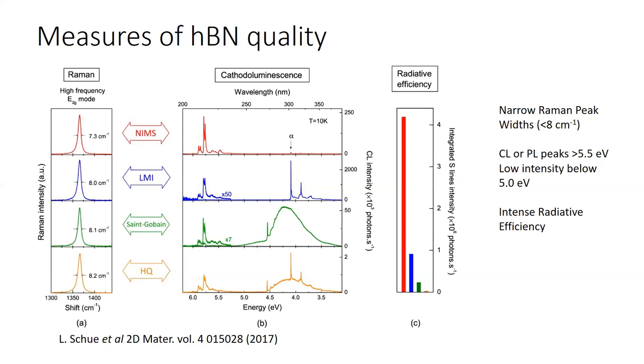In cathodoluminescence, you want high intensity above about 5.5 eV and low intensity below that, and then high overall radiative efficiency.